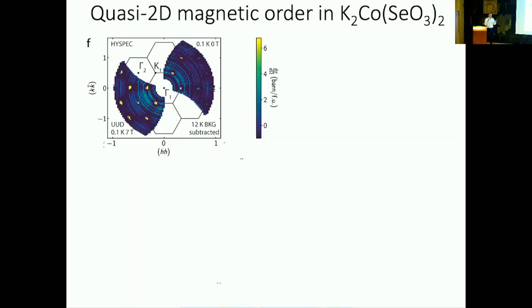Okay, so now we begin to look at some data for this actual compound. This is the triangular lattice material. I'm showing you data here both at 0 Tesla and at 7 Tesla. I've subtracted low temperature minus high temperature, and you can see little additional peaks that appear there. There's kind of a hexagon of peaks here that are already there in zero field. The fact that these are really sharp in momentum space indicates a long correlation length in real space. So there are some fairly long correlations that have developed.